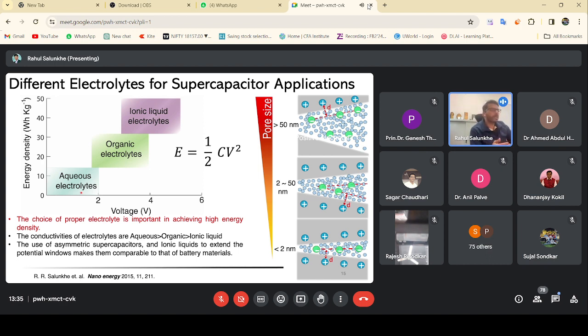The use of asymmetric supercapacitors and ionic liquids to extend the potential window makes them comparable to battery materials. There are certain reports in the literature that achieve energy density up to 60 or 80 watt hour per kg, but research is still going on in this direction on how these materials can be commercialized, and their cycle life performance, which are very important things to consider for commercial-level application.